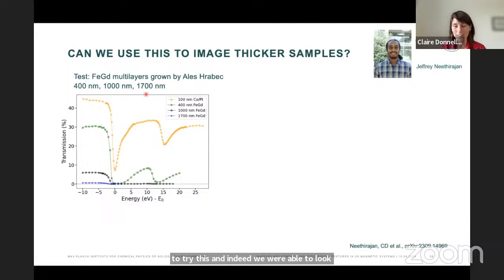So we went on to try this, and indeed we were able to look at a variety of different iron gadolinium multilayers grown by Ales Hrabec. You can see as we go thicker with the film, yellow is already 100 nanometers, and we go to blue, which is almost 2 micrometers in thickness. On resonance, we basically get 0 transmission. But even at 2 micrometers, we get a little bit of transmission in the pre-edge where we expect this phase signal to be.